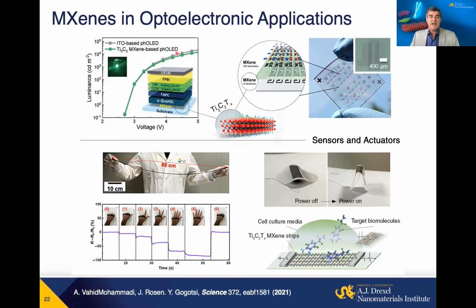For example, I mentioned that MXene are highly conducting and transparent in thin film. And we were working with Korean collaborators to show that it's possible to replace ITO in organic LEDs, and we get pretty much the same performance as ITO, but now the devices are flexible, and all the manufacturing can be done simply by solution processing, by a compatible process, and it doesn't crack when the device is deformed here. We can replace gold or other metal current collectors on flexible transparent substrates with MXenes. It's possible to make gels, hydrogels, aerogels, and you see this is a highly stretchable gel that can be used for strain sensing here.